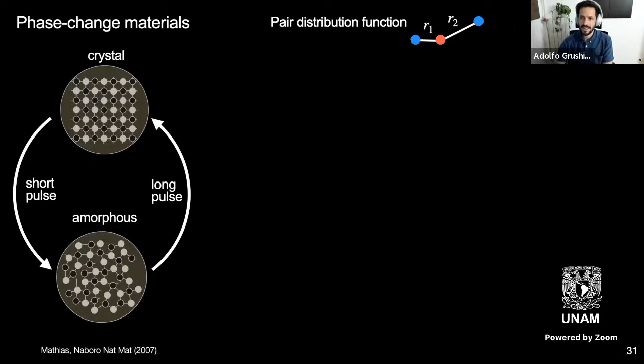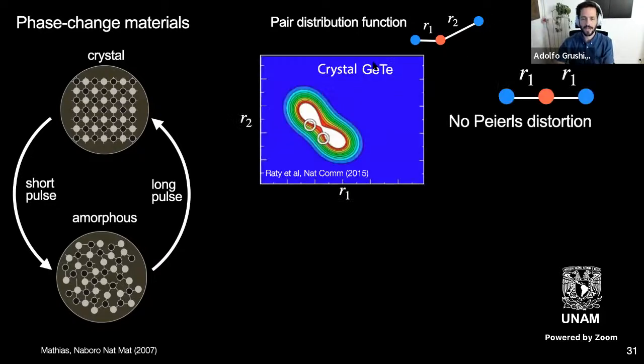And so one of the things that you notice is that the pair distribution function has actually different features in the crystalline and the amorphous phases. So the pair distribution function just tells you how likely it is to find the nearest neighbor from, let's say, the atom you started compared to a next nearest neighbor. And in crystalline germanium tellurium, which is one of these phase change materials, you have essentially a central blob that maybe it's a bit skewed, but it tells you that there's basically one length scale.